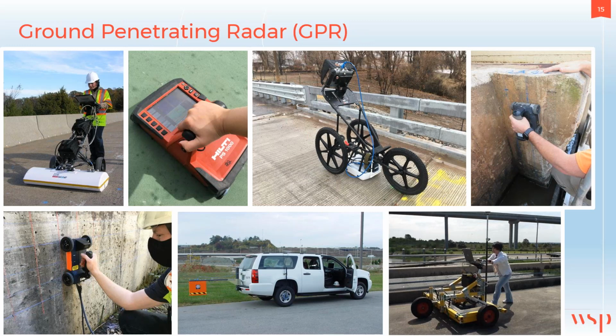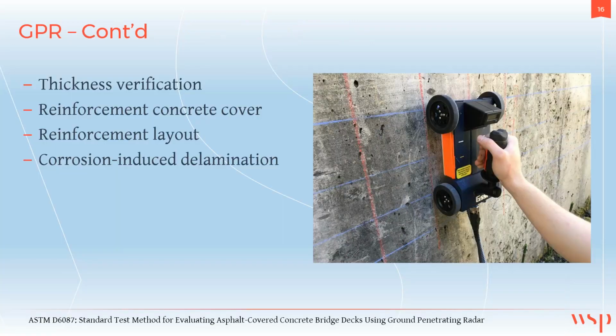It's often used to find embedded items, particularly reinforcing steel in reinforced concrete elements, and sometimes to also look for areas of potential degradation. Moisture tends to attenuate the signal in concrete, so if you have delaminations with significant moisture, that can be picked up. You can determine thickness of layers. It's not as useful as stress waves for directly detecting depth of delaminations or defects, but it does give some indication. It can also be used to infer things about corrosion thickness.